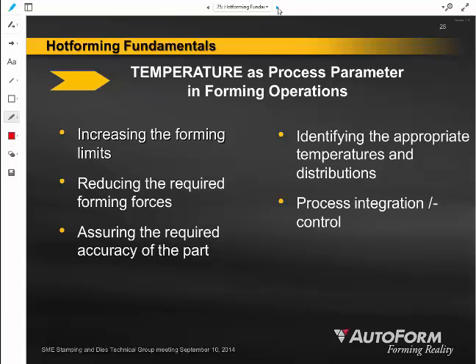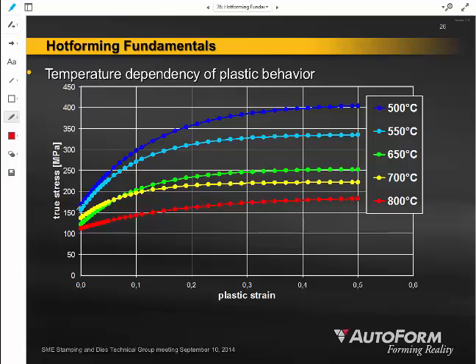So the thing that happens is that as we start looking at this type of deformation, it adds a new layer, a new level of complexity to our metal forming operations. We are going to end up having to understand that temperature is now an additional process parameter, one that we'll have to plan for and try to control and try to make sure that we can predict how the temperature is going to affect this forming operation and the product performance. So that means that we have to have material characteristics mapped out for that part at different temperatures that we might see throughout the forming operation. So that means a much more complicated methodology of testing our material as it comes in before it comes into our mill, and the ability to predict how that material behaves stress and strain wise at 800 degrees Celsius compared to 500 degrees Celsius.